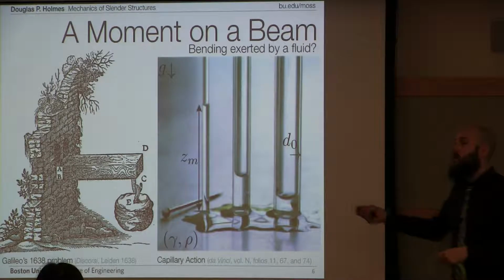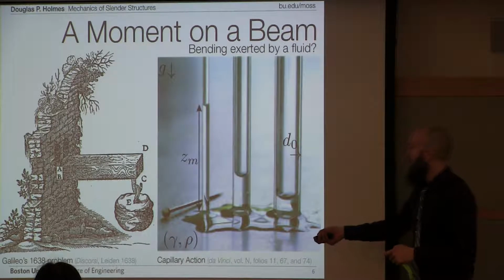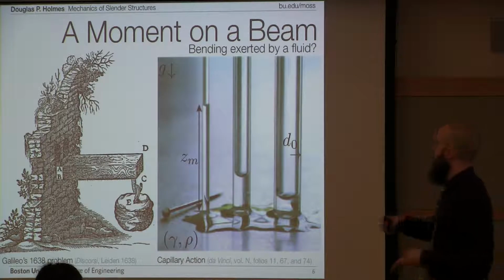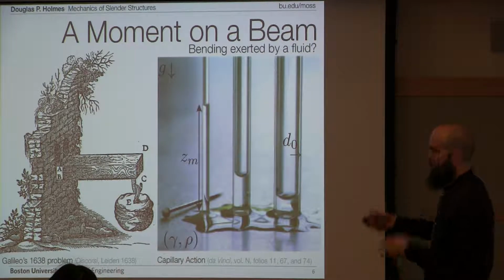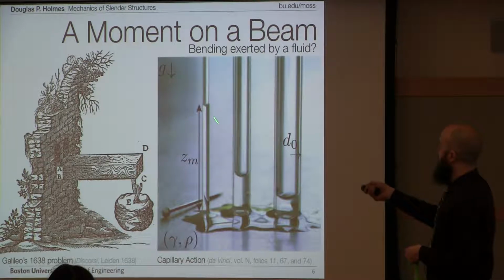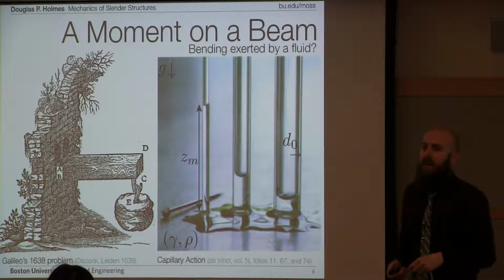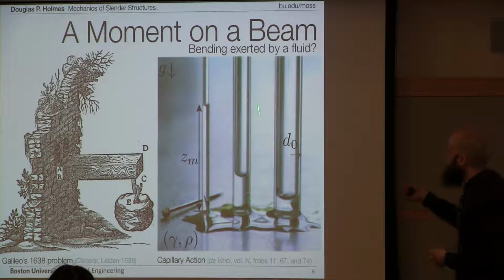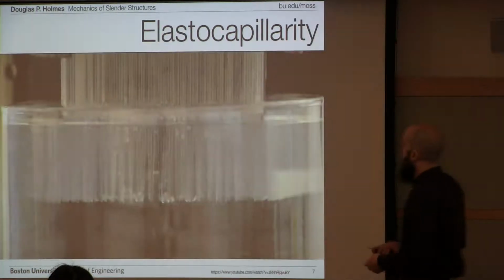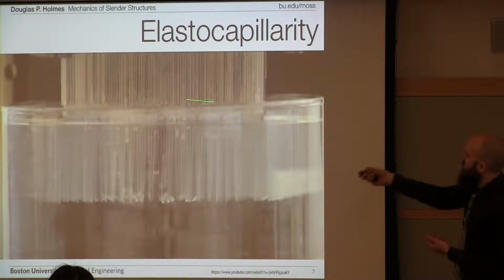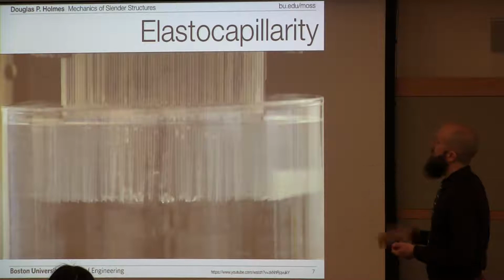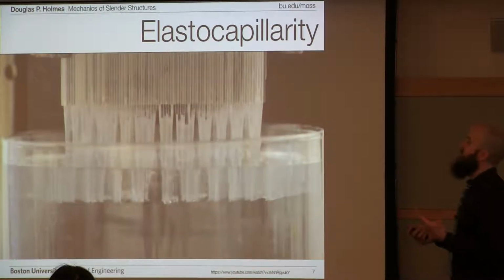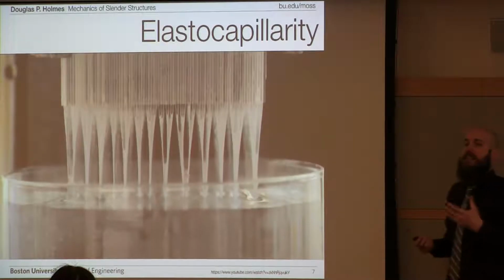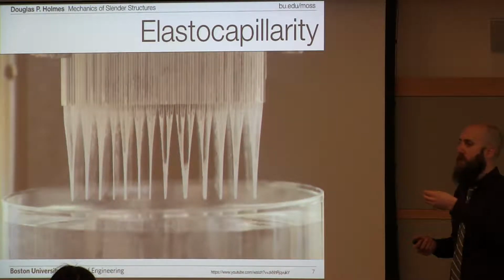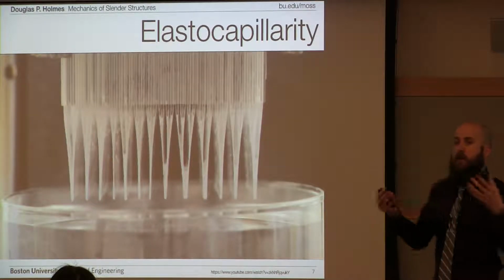So another really classical problem in mechanics, dating back perhaps to Da Vinci, who observed in his notebooks this capillary action, is how high will fluid rise if you put it within a straw. And as that straw diameter gets bigger, the fluid rises less and less high. And so the question that you can ask is, well, what happens if the walls of this straw are not rigid, but they're flexible? And what you see is you have a bunch of flexible sheets here. They're sitting in a bath of fluid. And if you just pull these sheets out of this fluid, you get a coalescence of these sheets. And this is the exact same behavior that happens when you take a paintbrush and you dip it in a bucket of paint, or for those of you with hair, when you get out of the shower and they stick together.